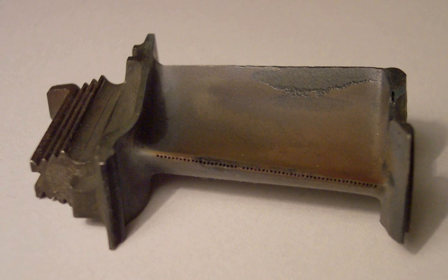Chromium is also used in cobalt-based superalloys, occasionally up to 20 wt%, as it provides oxidation and corrosion resistance, critical for material use in gas turbines. Gamma prime, γ', just as in Ni-based superalloys, this phase constitutes the precipitate used to strengthen the alloy. In this case, it is usually close packed with an L12 structure of Co3Ti or FCC Co3(Al, W), though both W and Ti have been found to integrate into these cuboidal precipitates quite well.